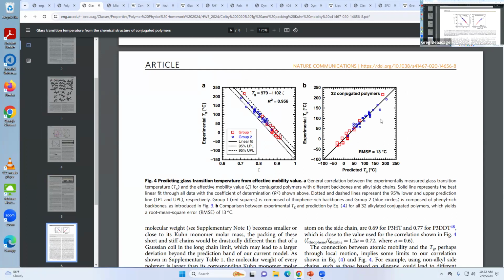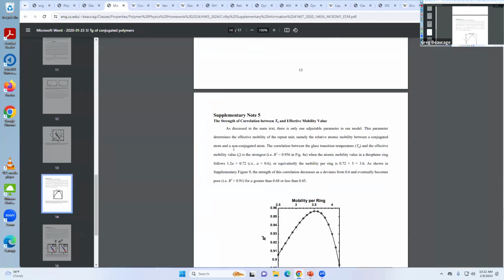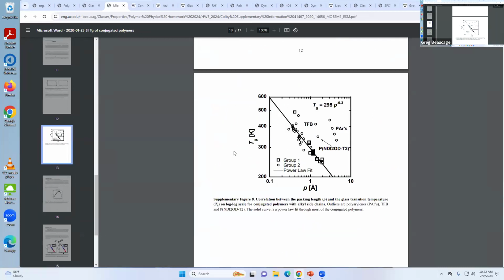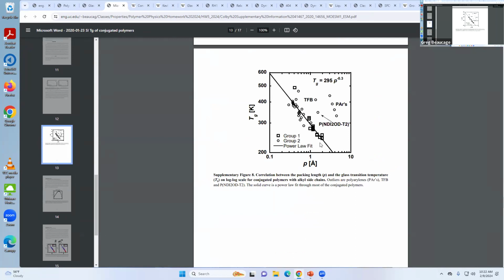It's kind of nice. And then when they compare their calculated TG with the experimental, they find a 13-degree root mean square difference. It's not bad, especially when you look at the thing they compare it with, the packing length, which is like here. So the packing length isn't bad. Actually, it looks pretty good. So they say take TG and the packing length, and you get a power law decay of roughly -0.3. Okay, so anyway, that's kind of interesting.